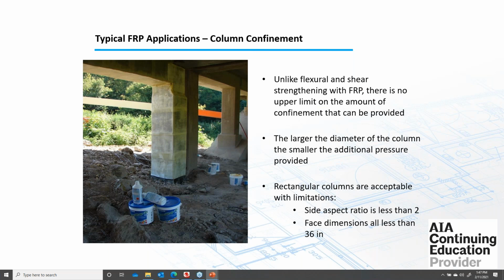Here's an in-practice view of that. This is a double column, so you can see there's a column and then another column immediately adjacent to it. There's probably only maybe an inch or two in between those columns, about 50 millimeters or so, which is really all the room you need to be able to install the FRP. If you can fit a paint roller in the space, you've got enough room to install a system. So it's a really versatile material as far as the installation side, which Hamza is going to get to in a second.